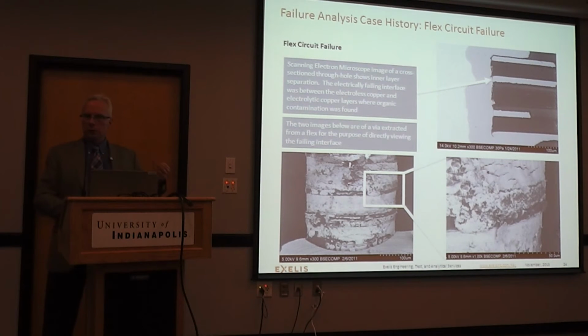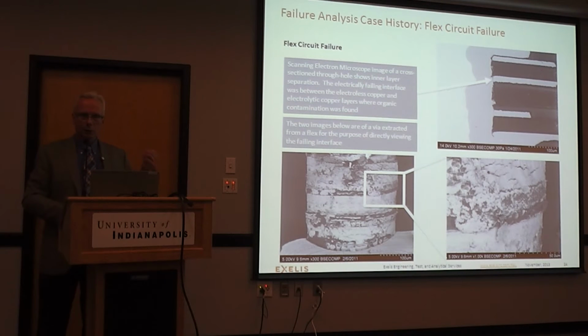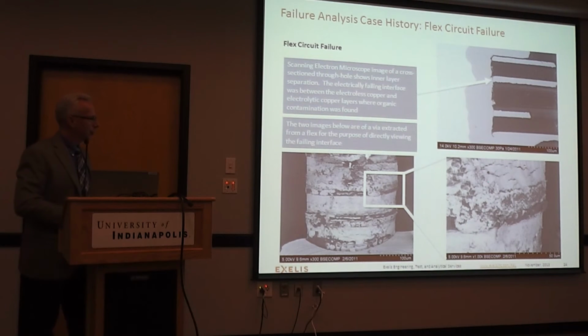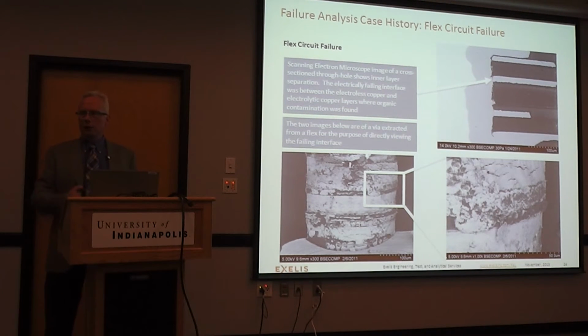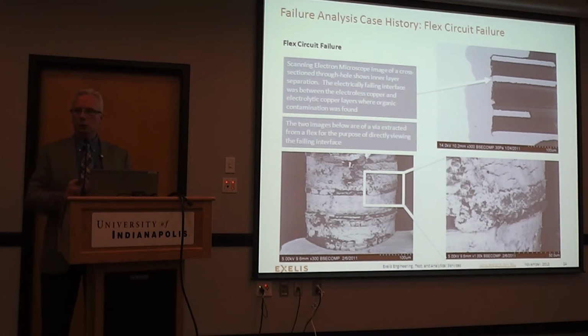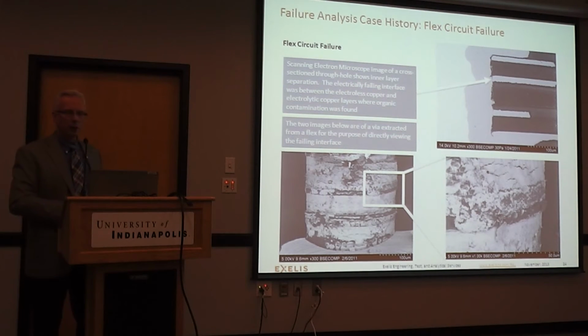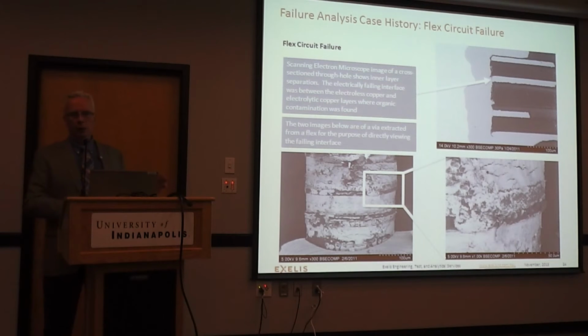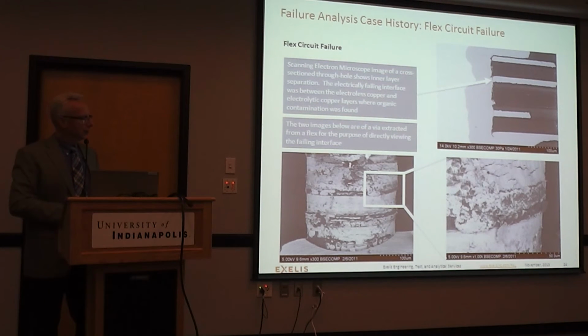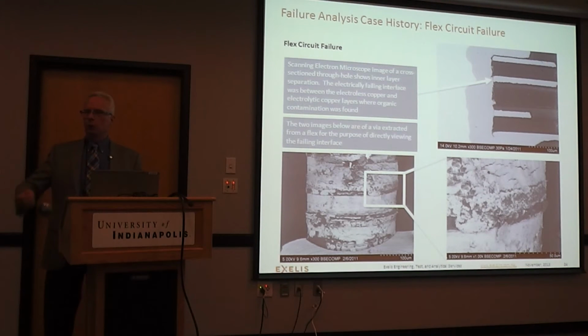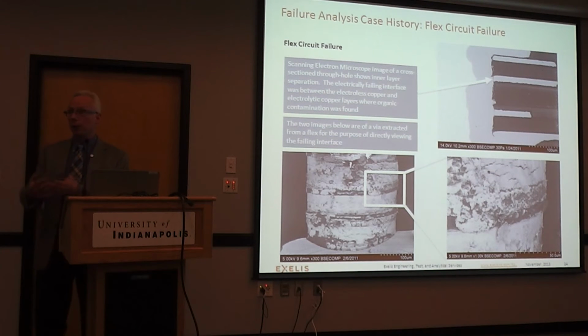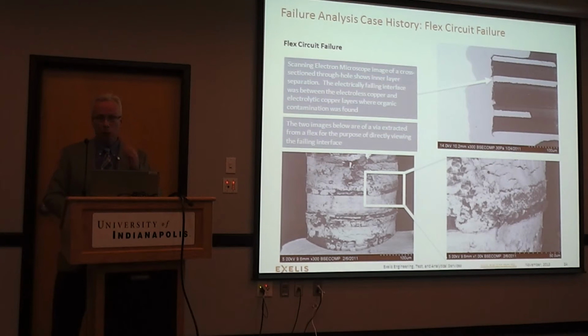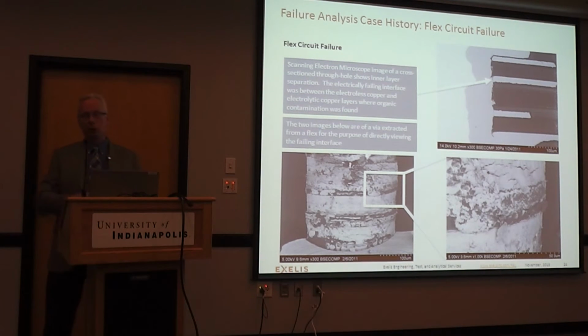Okay, so the flex circuit failed due to an open plated through hole, due to a T-joint problem, and the T-joint problem was related to organic material within the T-joint. And so, without disclosing too much supplier information, we ended up conversing with the supplier of this flex circuit and found out their bill of materials, all the chemicals and materials used in the manufacture of this flex circuit. And by doing an infrared FTIR analysis, which stands for Fourier transform infrared spectroscopy, we identified that material and traced it to a material used in their process, which gave us insight into which step in their fabrication process caused that problem. So ultimately, we traced it down to a step in the process.